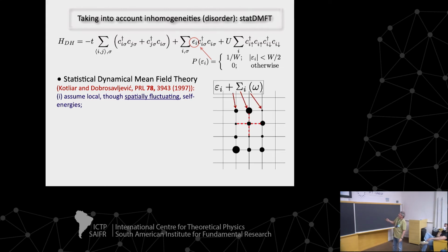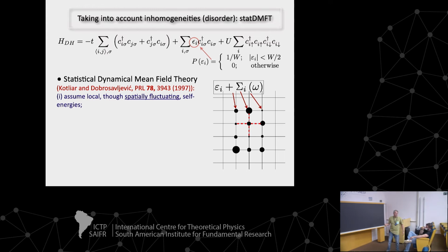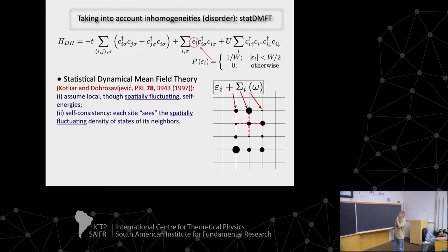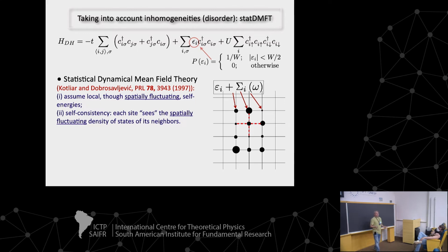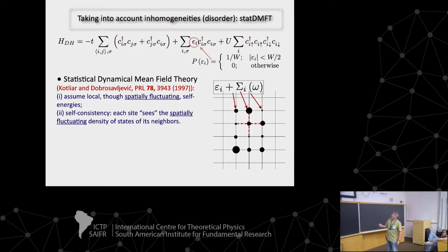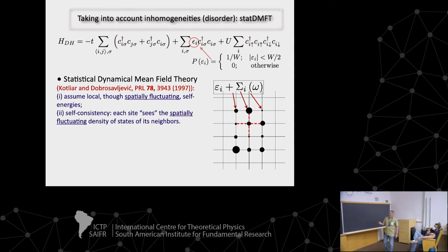So pictorially, if you think of the self-energy as the size of those circles, this is the best I can do, I'm not a very good artist, you have small circles and large circles like that, depending on the environment where you are. And then the rest is basically the same. You solve the problem for this site in the bath of the other sites. This is the hard part. And then you impose self-consistency. But note that as you impose self-consistency now, the sites are not the same. So the environment of this guy are these other guys here. This is a much, much tougher problem to solve. You basically have to solve one single impurity problem per site and then impose self-consistency.